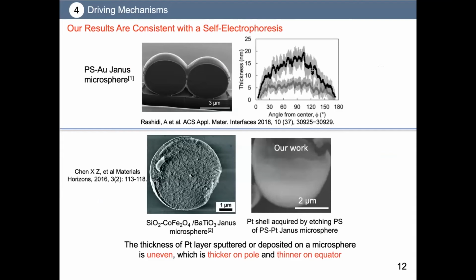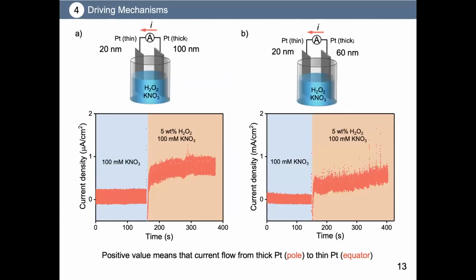And finally, we suppose that self-electrophoresis may be the dominating mechanism. First, according to literature and our experimental results, we confirmed that the thickness of platinum sputtered on a microsphere is uneven, which is thicker on the pole and thinner on the equator. So the different thickness of the platinum layer leads to non-uniform decomposition rate of hydrogen peroxide, which would generate a net current flow from the thick pole to the thin equator.